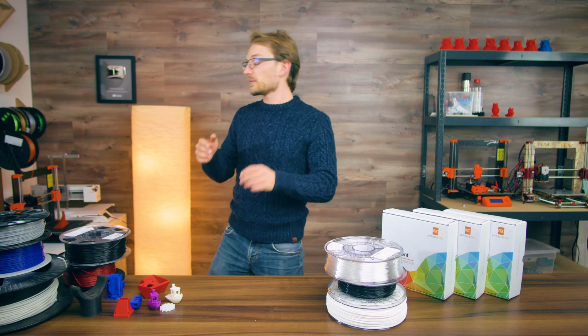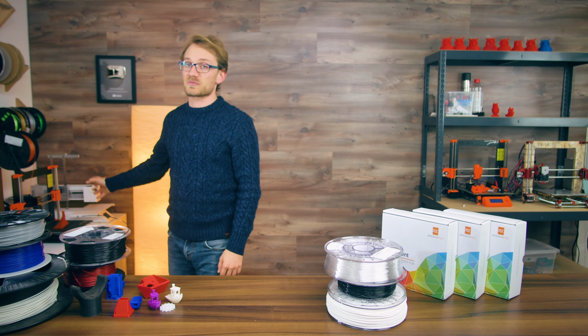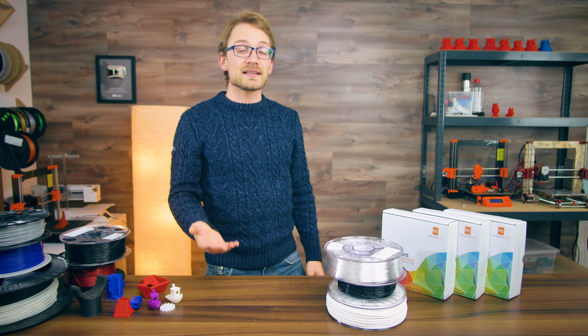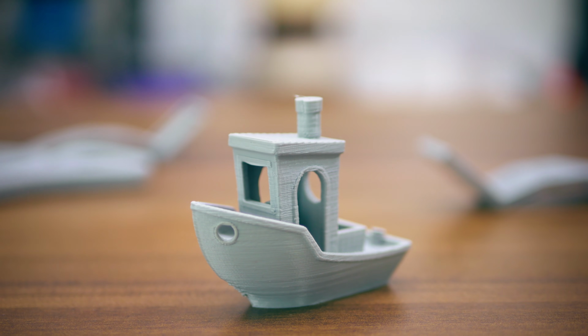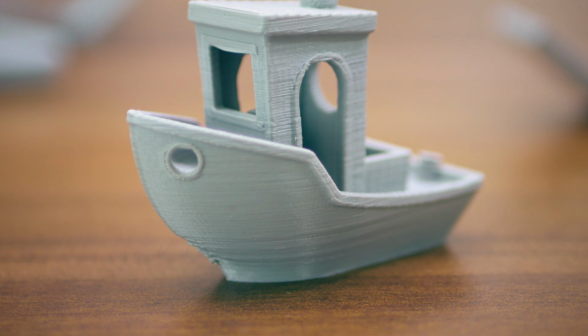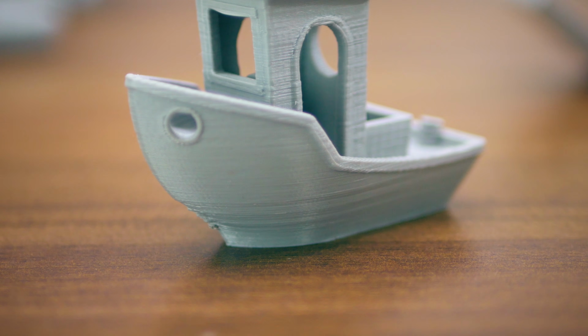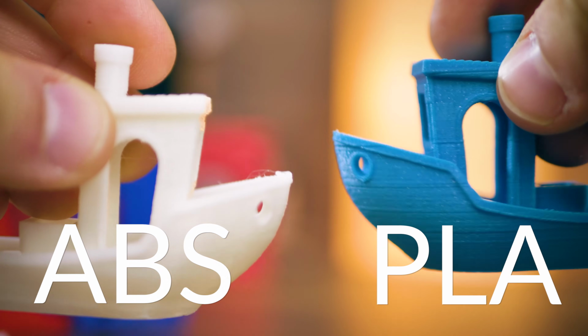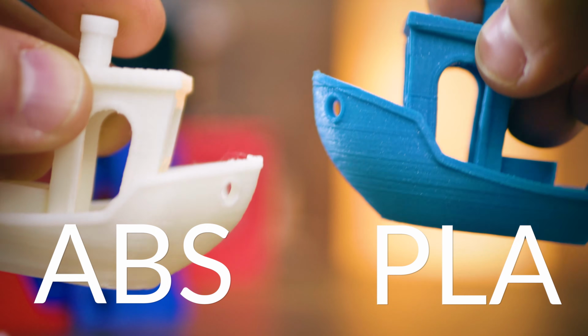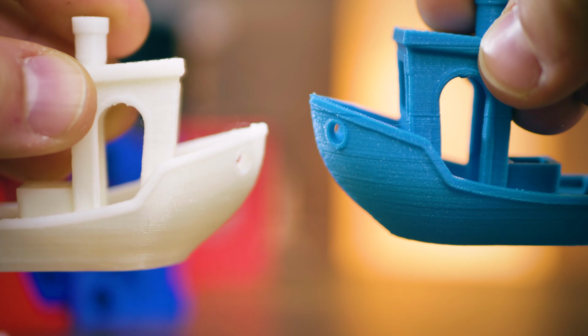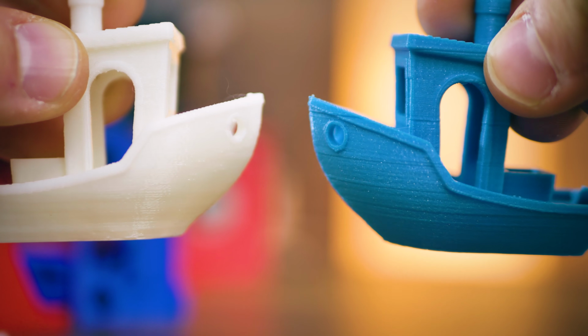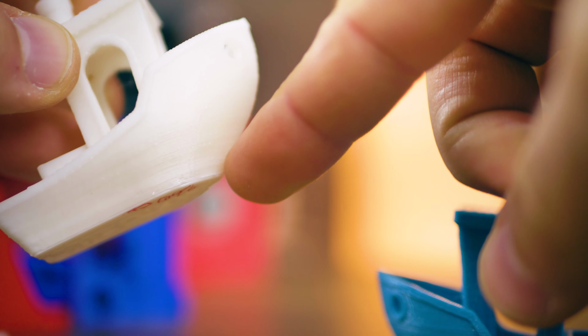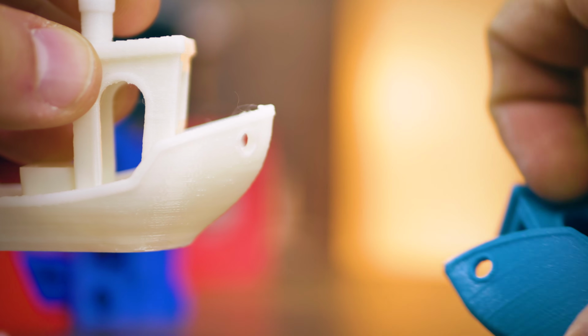We used to crank these babies up to 120 degrees Celsius, but with most materials, that leads to what is often called an elephant's foot. And I'm not talking about nuclear meltdown here, but it's when the very first layer of the print sticks well to the bed, but the bed is so hot that the first few layers above it end up staying soft and contract as the print progresses. A heated bed that is too hot will also ruin any overhangs that are close to it because those will curl up.